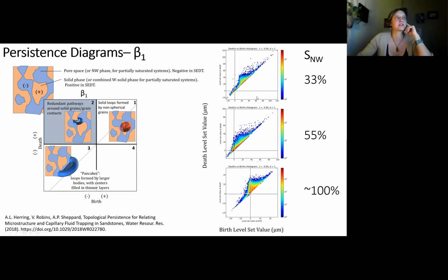Right. Yeah. So in this case, for these diagrams, these were all quasi-static flow experiments. So some fluid injection, and then an equilibration period so that we don't get interfaces moving in the scans, and then one scan. Each diagram is just based on the non-wetting phase distribution in that quasi-static state. So it's not under continuous flow conditions. The microCT systems that we have are not built for speed of scans necessarily. Each scan for this case was about an hour, maybe 2 hours, but we tried to ensure that the fluid states were stable during the scan acquisition.